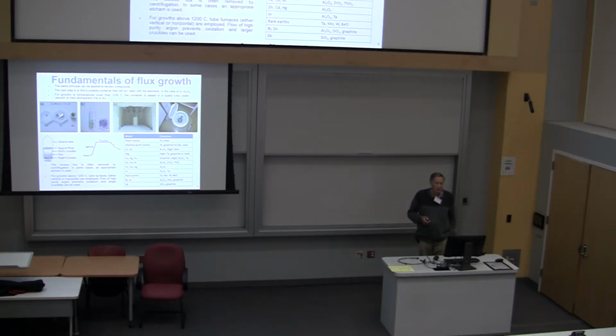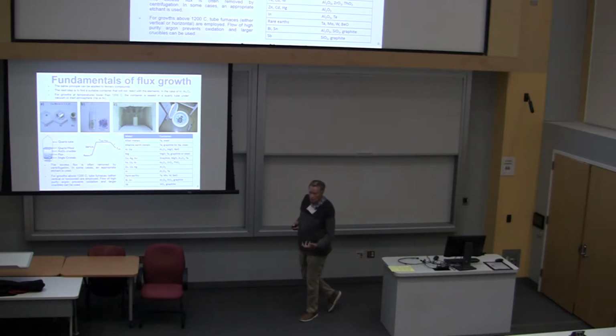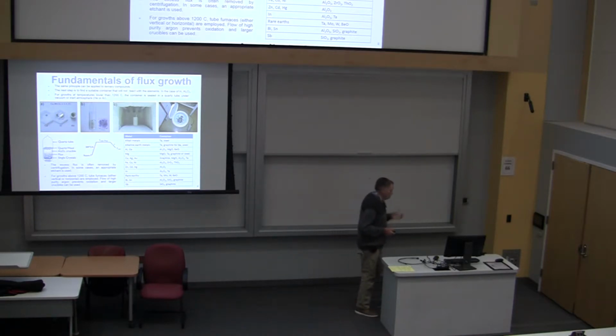It turns out that if you look at the cerium cobalt phase diagram, there's a very deep eutectic, somewhere around cerium 3 cobalt, that you can actually use as a flux for growing certain other compounds. And it's also easy to get rid of chemically, it turns out.